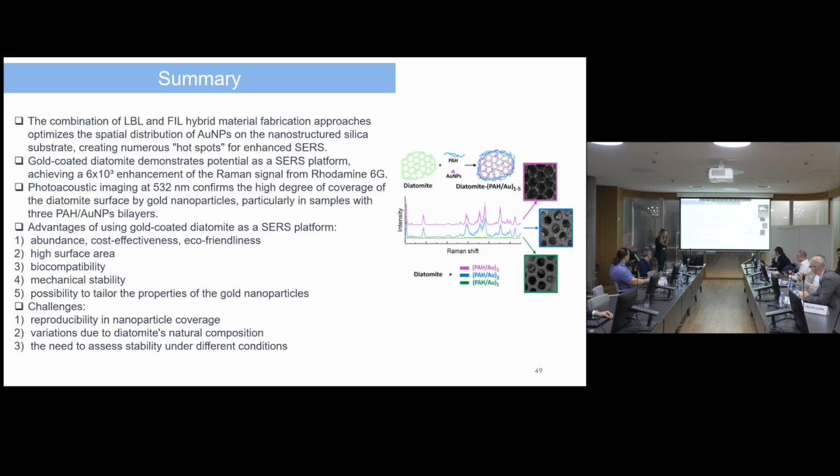First of all, diatomite is highly abundant. Then cost effectiveness, eco-friendliness. Diatomite has high surface area. It is biocompatible. It is mechanically stable. Also, when it comes to the gold nanoparticles, we can tailor their properties, which can also influence the reproducibility of SERS enhancement. However, the disadvantages include reproducibility in nanoparticle coverage. We did not achieve a completely uniform distribution of such gold nanoparticles on the surface of diatomite.